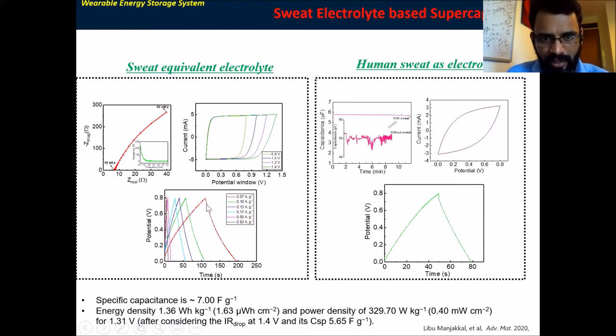And then you can see here the charging discharging analysis. And then a question came. When we are using human sweat, depending on the person, the amount of sweat may vary. So initially I noted that without much sweat, the device is in the picofarad range, almost very low. But when you are sweating, the ion content is increasing, and you can see here it's almost reaching the microfarad range. And here this is real human sweat. We did the test, and here is the quasi-rectangular shape, and also you can see the charging discharging analysis.